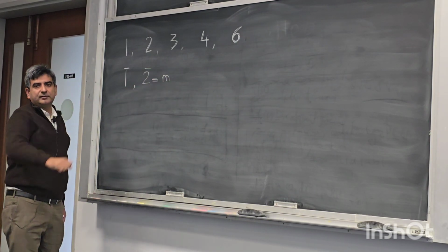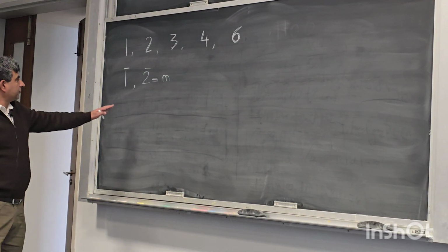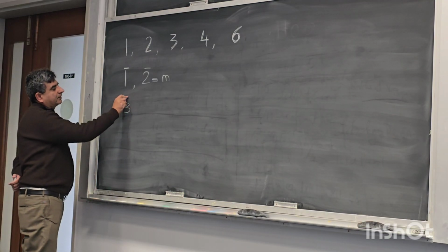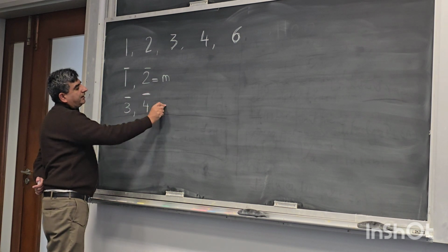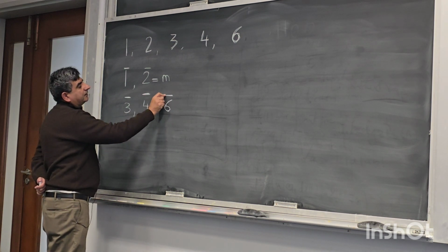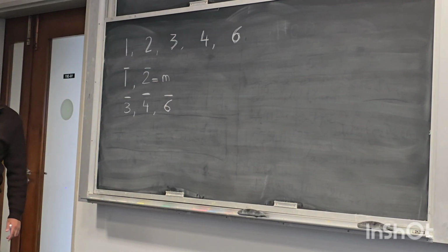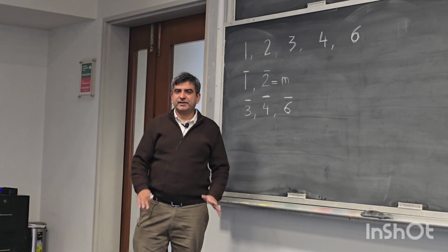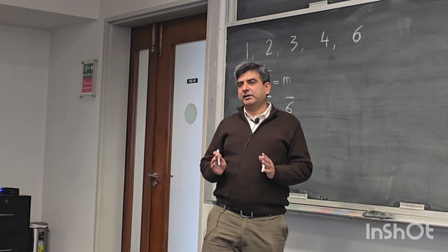So this is a plane, and we also have inversions: 3 bar, 4 bar, and 6 bar. Each one of these inversion operations is a rotation followed by an inversion. So these 10 point operations exist inside solids, and these point operations determine the macroscopic symmetry of crystal.